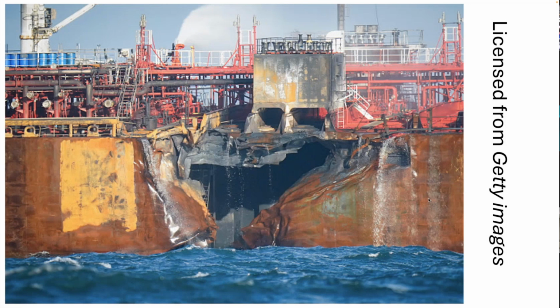It's really got into a convoluted shape, fractured into a large gash, and so forth. And that is really quite important because the deformation of the steel absorbs energy. And notice that this ship is still afloat. And indeed, both ships remained afloat and were towed into harbor somewhere in Britain. Now, this level of damage can only be sustained by something like steel. There's no other material which can take this level of damage and yet keep the ship intact.